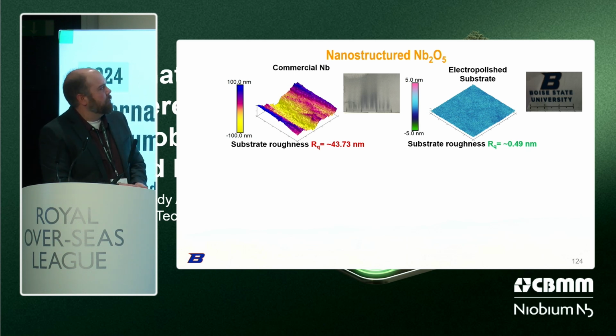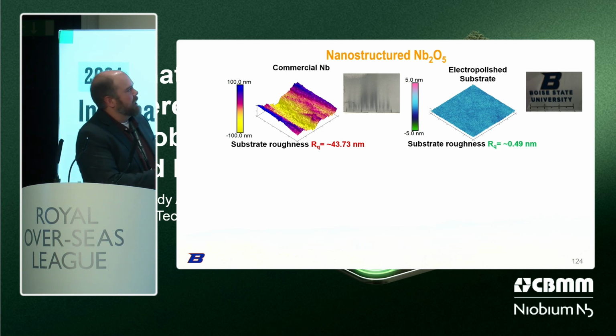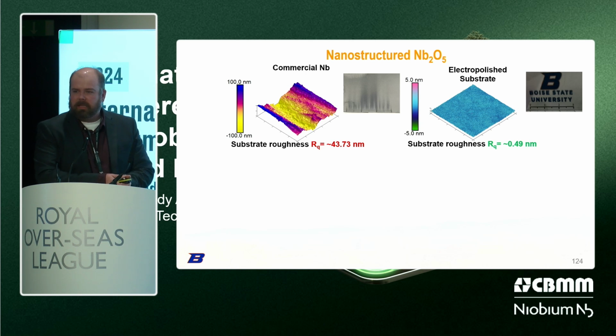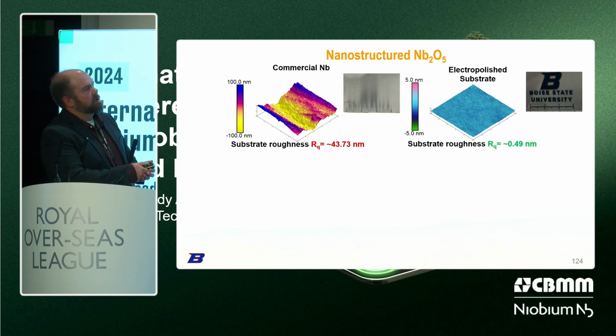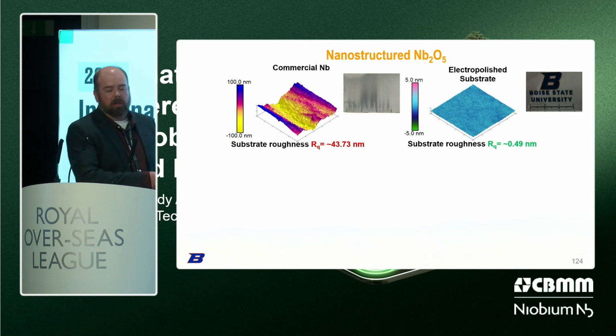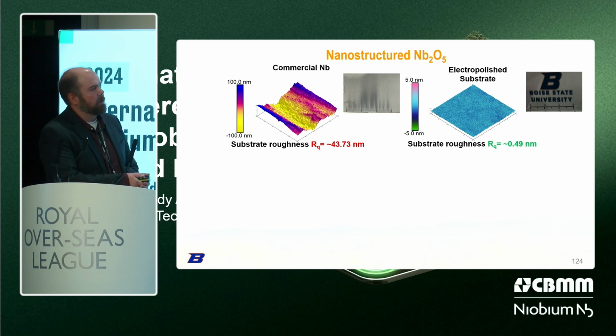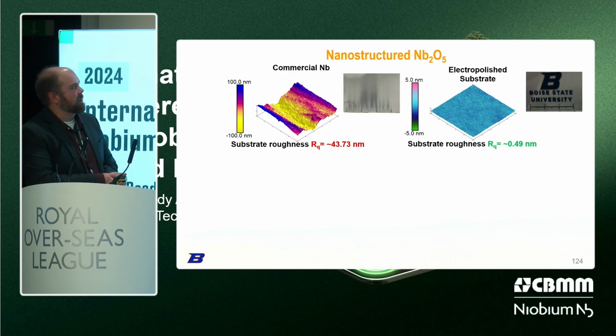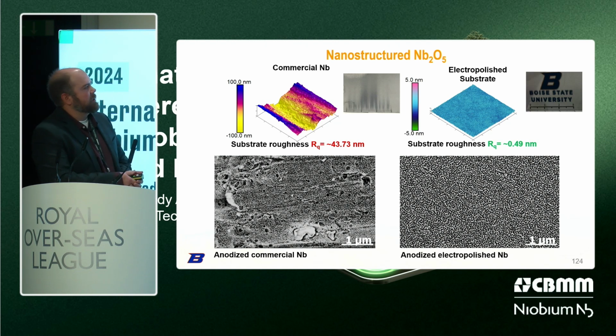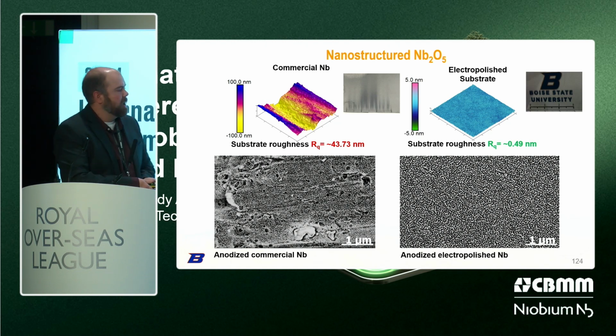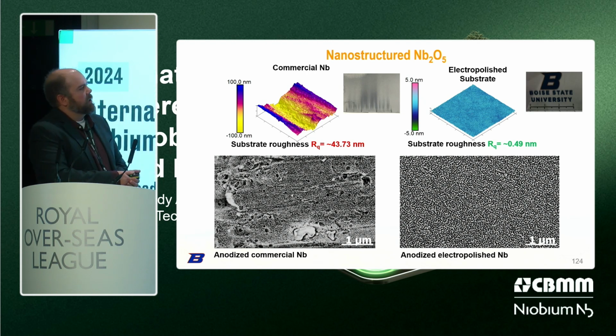It wasn't very uniform. What we found out is that the commercial niobiums we were getting are quite rough, right? They have about 44 nanometers of roughness, even though they're one of the smoothest we could get. So we developed and pioneered a method of electropolishing niobium materials down to about 5 angstroms in this 5 micron by 5 micron AFM image. In a hot glycerol phosphate, potassium phosphate solution, we go from these not really nice structures to this very uniform anodized niobium metal, niobium oxide.